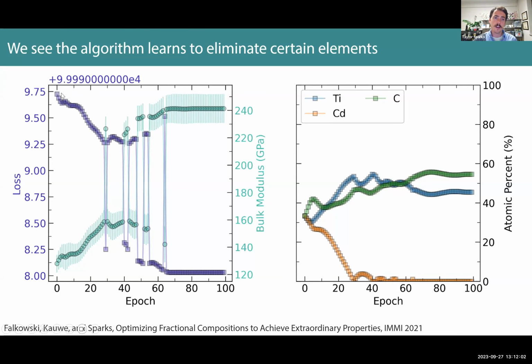And we're seeing that it goes down. It really, at one point, kind of figures it out, and then the loss drops. That's because in this problem, we were asking it to maximize bulk modulus. And you can see on the right-hand plot of that, it's actually increasing. All of a sudden, it really figures out how to maximize bulk modulus.